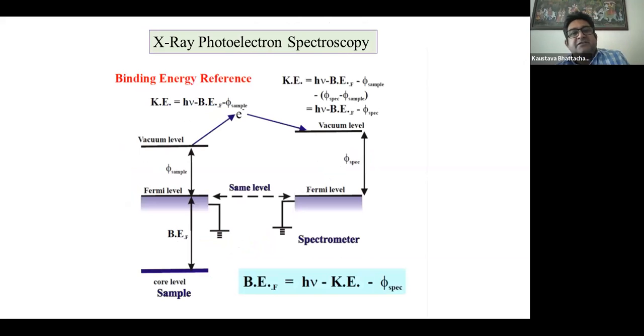So if we have that system where we have a core level, a Fermi level, and the vacuum level, and we have the same instrument, the vacuum level of the material and the vacuum level of the spectrometer should be merged. Equivalently, this kinetic energy will mostly depend on phi, that is the work function of the spectrometer, rather than on the work function of the sample. So this is constant, and the binding energy of the material will directly depend upon the kinetic energy. Experimentally, we are measuring the kinetic energy of the material, and we know the source energy. The work function is almost constant for a particular spectroscope. So we can exactly find out the binding energy of the material from this equation.